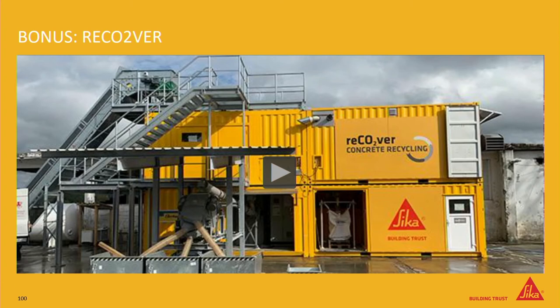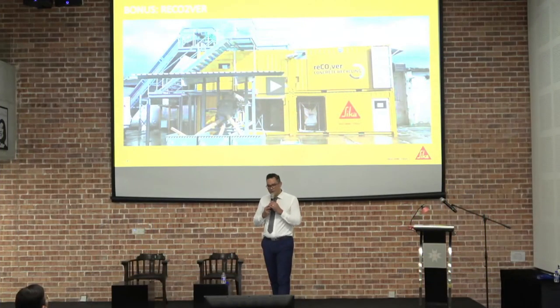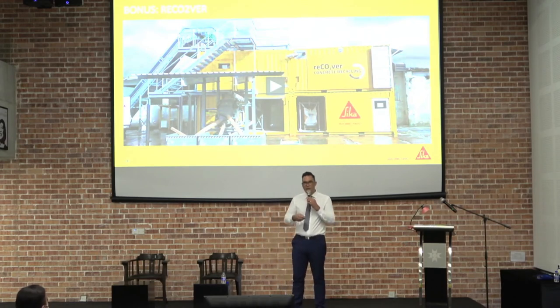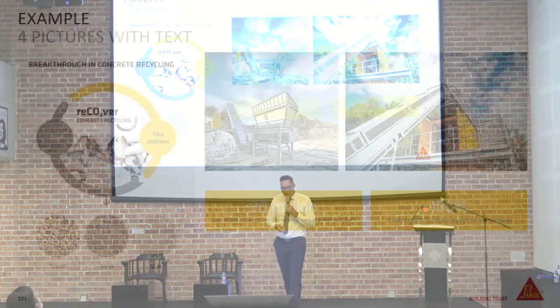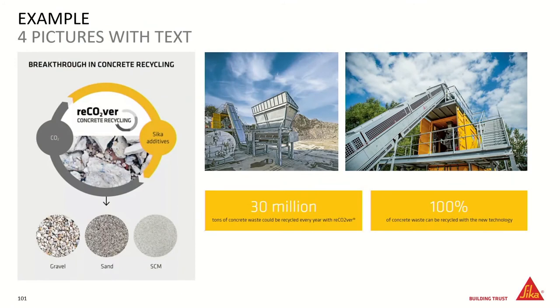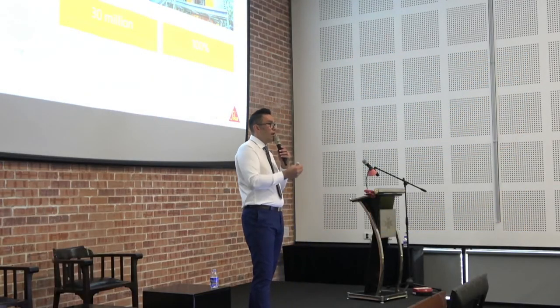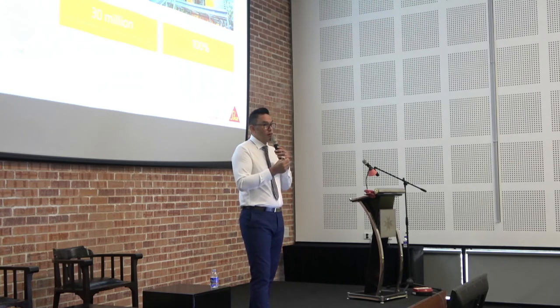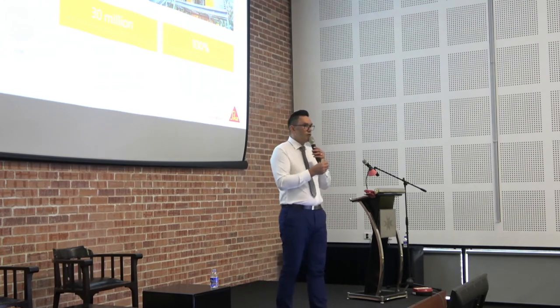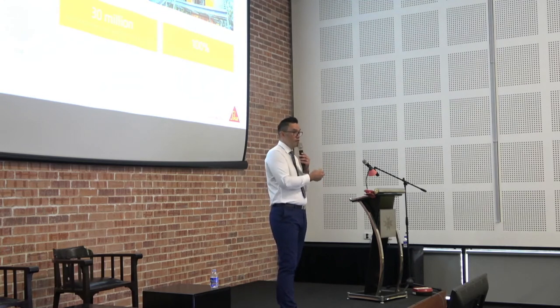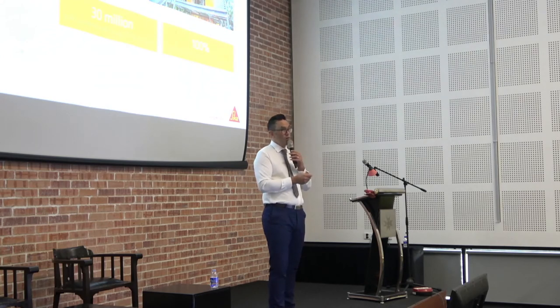So in answer to the earlier question about the sustainability, part of that sustainability is also looking at ways that we can work with this construction demolition waste. And the reCO2ver is a technology that Sika have to deal with that and capture some carbon. So we take the waste from construction, returned concrete or broken buildings, rather than landfill, we put it through the process. And the big issue with recycled concrete is it's very porous, so it absorbs a lot of moisture that you put into your concrete mix, so you have to allow extra water because all the cement paste is not taken off. With reCO2ver, it takes off all the paste and you're 95% back to a virgin state aggregate. So now you can put it back into the process and almost do identical mixed design as if you just mined that material. So it gives you the advantage that you can use a recycled aggregate in the same mixed design as a brand new aggregate.